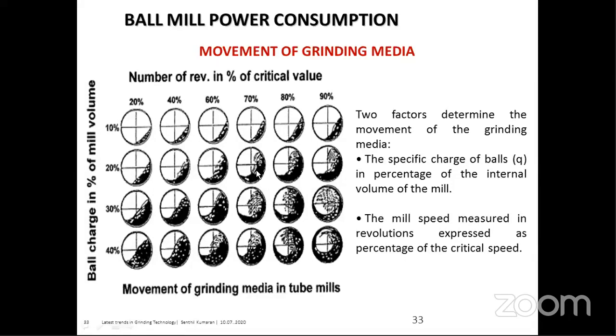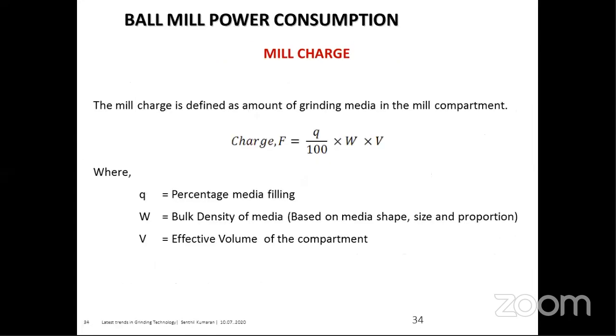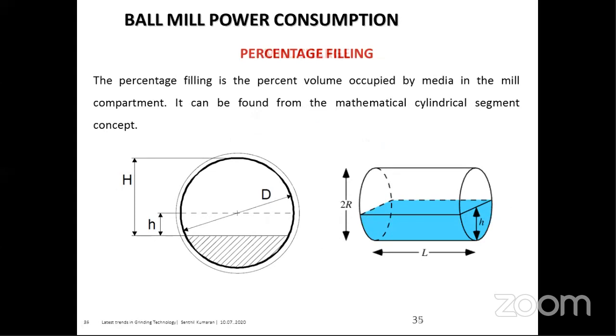At 20%, between 70 to 80, where we target, the impact happens, but not up to the mark. At 30%, the mill rotates, the media lifts up, and it effectively falls in the charge. So the effective grinding occurs between 70 to 80. Based on experience and the different liners and suppliers, the percentage of the critical speed is chosen. So this is the mill charge, which typically will be 30% of the mill.